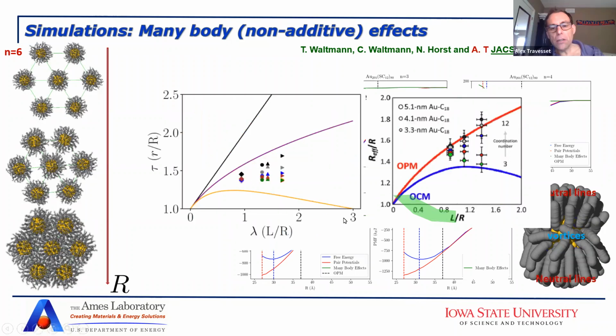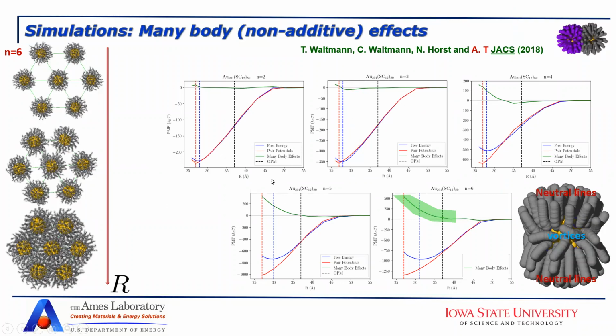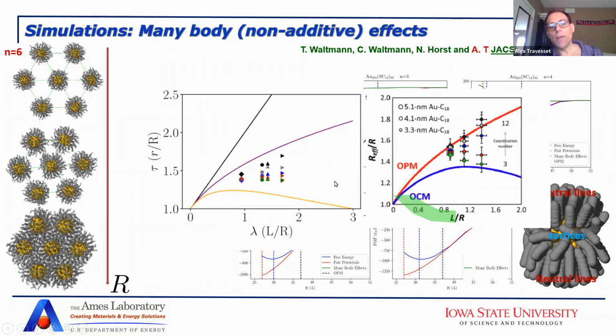You can see here that the separation between nanoparticles increases with coordination. That's another manifestation of many-body effects. In fact, if you plot the separation in terms of some unitless variable, you see that the higher the coordination, the farther the particles are. This completely agrees with the experiment. And this line here represents what would be the hard sphere. So here what you see is that at coordination 6, basically, you already are in the hard sphere limit. So that's when the particles behave as hard spheres.